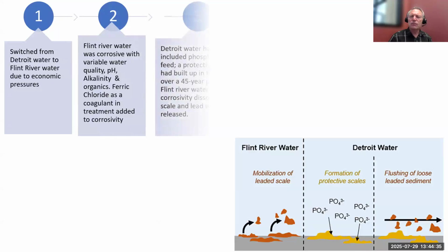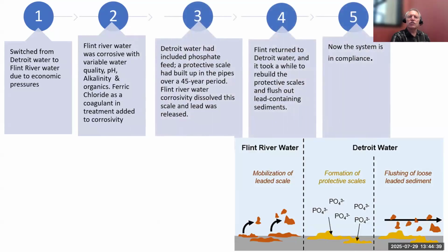Now, Flint, there's a little story here. They switched from this Detroit water source, which was kind of like they purchased treated water, to the Flint River, where they already had a treatment plant constructed, and that was mostly because of economics. The Flint River was kind of unstable and corrosive. It had kind of higher organics, so they were also having problems with disinfection byproducts. It was kind of variable quality. But part of the treatment choice involved using ferric chloride as a coagulant, and they had a reason for doing that. They were trying to meet also disinfection byproduct rules and so forth, so they chose ferric chloride.